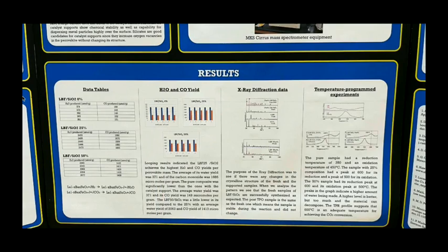The LBF silicon dioxide 50% shows a lower yield of carbon monoxide and water, and this could be due to an increase in formation of iron silicate and lanthanum silicate at the LBF silicon dioxide interface. The secondary phases can reduce the composite's ability to accommodate oxygen vacancies and its carbon monoxide generation capacity. But the LBF silicon dioxide 25% shows the maximum yield, demonstrating its minimal secondary phase formation and maximum wettability.